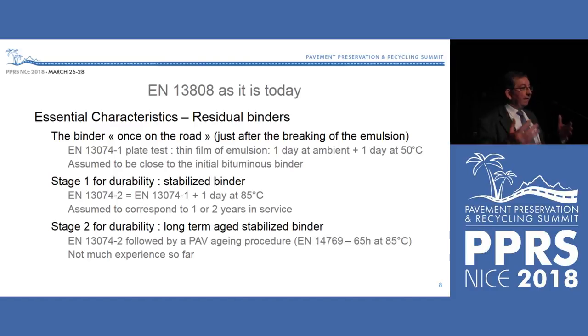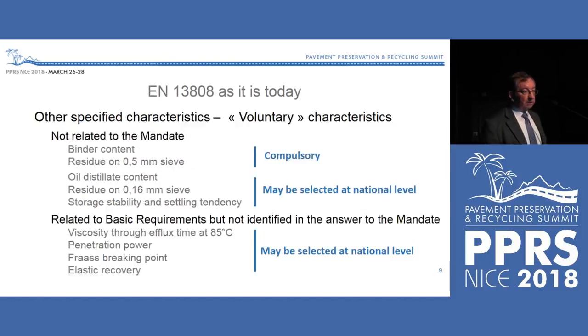You have sprayed it, laid it, you get the water out, and this you try to reproduce via a so-called plate curing test, and this binder is assumed to be the initial binder just once on the road. And then you enter into 2 possible stages for durability. The first one being a stabilized binder, which is obtained by just continuing the previous procedure by a further day at 85 degrees C. And the second stage, in which you long-term age the binder via the well-known PAV process. Unfortunately, so far there is not much experience on this one.